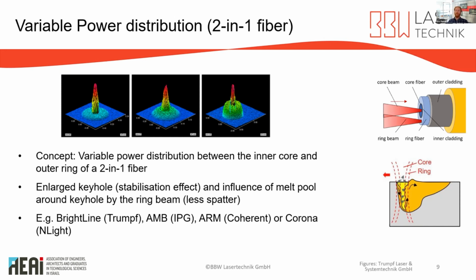The idea here is we have a variable power distribution between a core and a ring fiber using the 2-in-1 fiber. So it promises improved seam quality, reduced spatter formation. We have seen already that it, of course, reduces the spatter formation and increases welding depth. During laser deep welding, a widening and stabilization of the vapor keyhole is realized due to the power distribution of the ring fiber. So the molten material around the keyhole is influenced by the ring beam power with a contrary impulse and deflected to the backside of the keyhole.